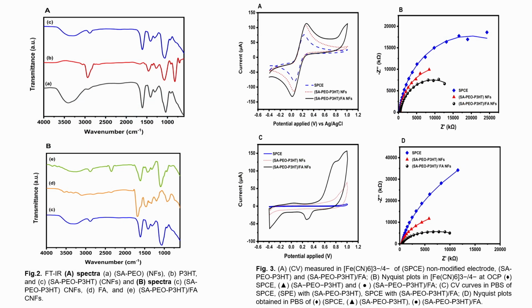And we continued with electrochemical characterization using cyclic voltammetry and the EIS technique. As we see, there is an increase in the current peak from the blue dashed curve for the screen-printed electrode without any modification to our conducting nanofibers layer in red, and it increases more and more after conjugation with folic acid. This is due to the increase in ionic conductivity due to folic acid and the nanofiber structure with the large surface area and porous structure, which allow the transfer of charge. And also the redox activity and the electronic conductivity of P3HT.